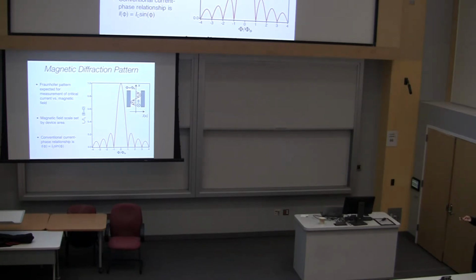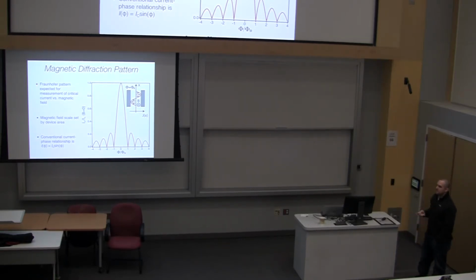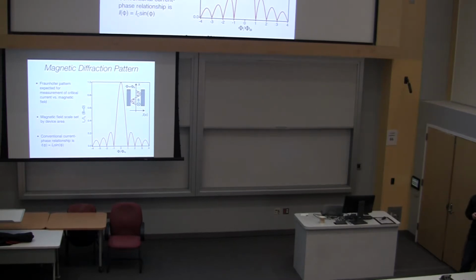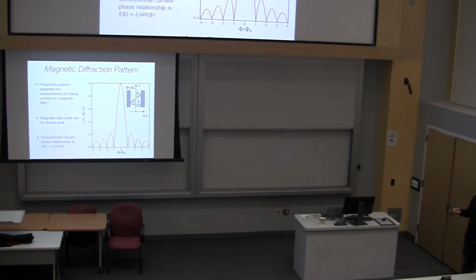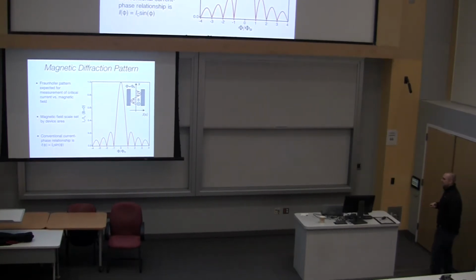So if you look at the pattern traced out for a junction that is uniform and has a sinusoidal current phase relationship, you see what's called a Fraunhofer pattern. This is the same pattern you get in a single slit diffraction. It's basically, you might remember, the Fourier transform of some box function representing the supercurrent through the device.